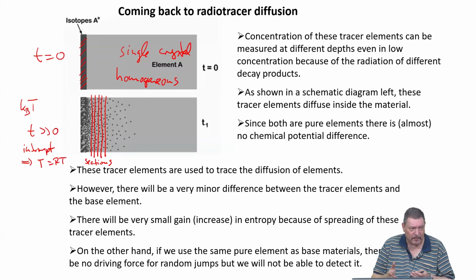This is one way. But this is only the way we use if there is a stable isotope, because the counting efficiency is horrible. So we get a very low sensitivity for measuring diffusion or for measuring marked atoms inside each section layer if we use this method. Much better is to employ detectors which are able to register the radioactive decay products.